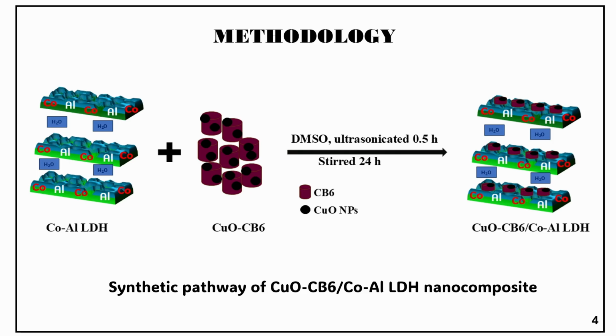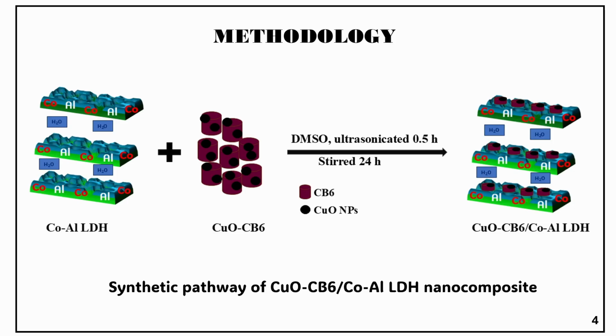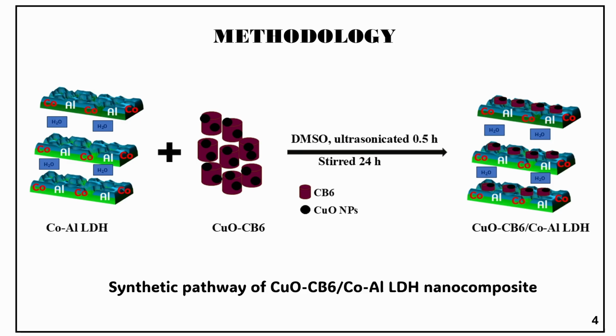Next, coming to the methodology section, this scheme illustrates the synthetic pathway for the CuO-CB6 cobalt aluminum LDH nanocomposite, starting from the precursor CuO-CB6 and cobalt aluminum LDH components. 3 different nanocomposites of CuO-CB6 cobalt aluminum LDH were synthesized using wet impregnation method with ratios of 1:1, 1:2 and 2:1 for comparison and analysis. The precursor cobalt aluminum LDH was synthesized separately using the urea hydrolysis method.